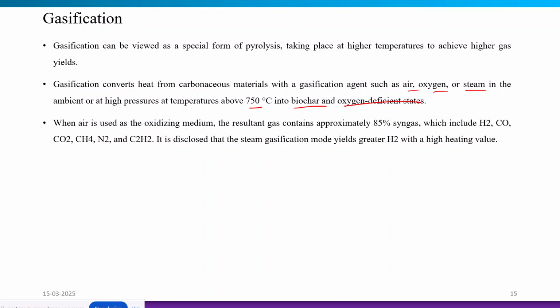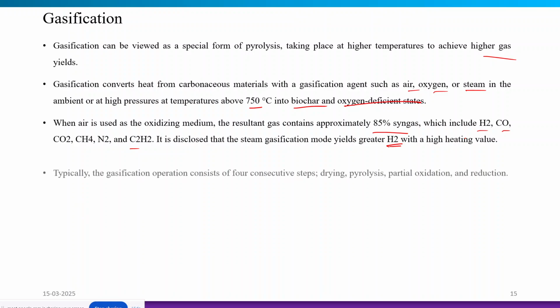So when we talk about gasification, it takes place at a high temperature. So we are getting more cracking of those carbonaceous materials, and we are getting more gaseous yield. When air is used as an oxidizing medium, the resulting gas contains 85% syngas, which includes hydrogen, carbon monoxide, carbon dioxide, some methane, and other lower molecular weight hydrocarbons. It is disclosed that the steam gasification mode yields more hydrogen, which has the higher heating value.